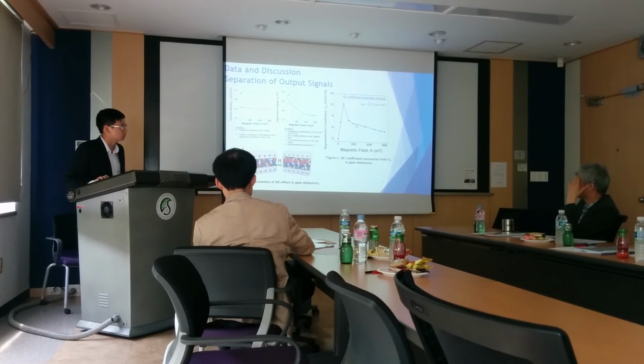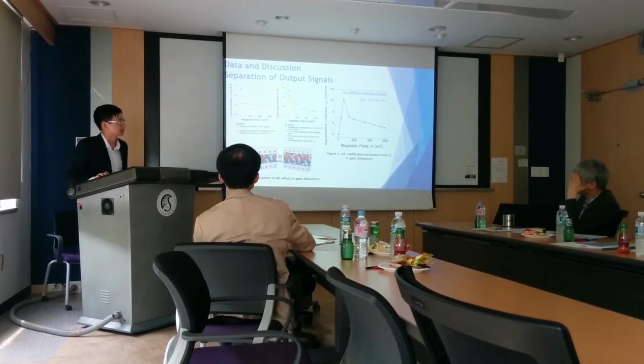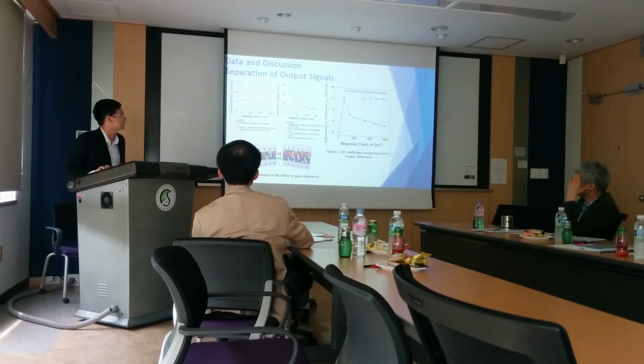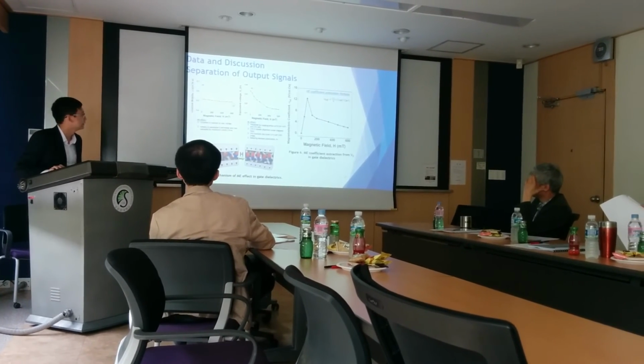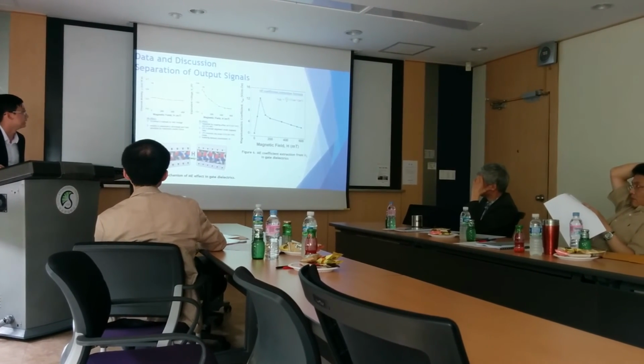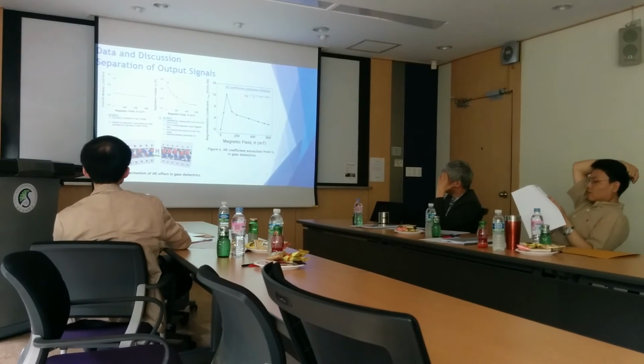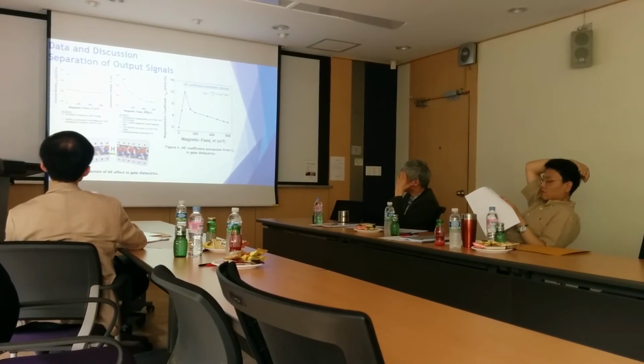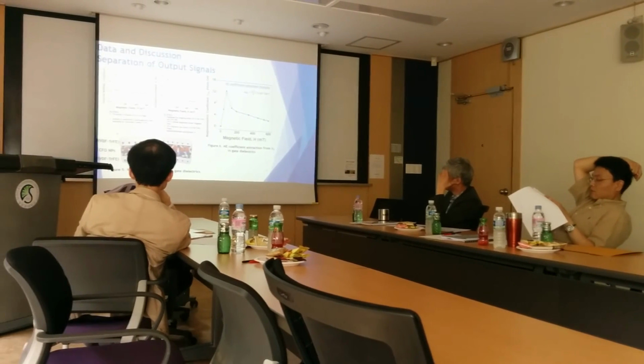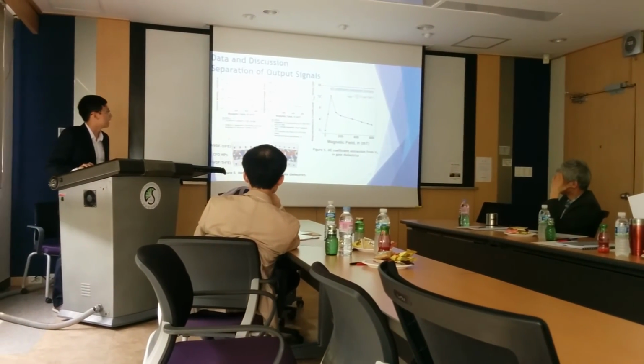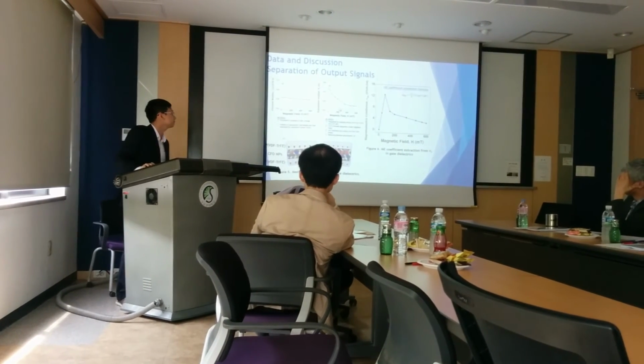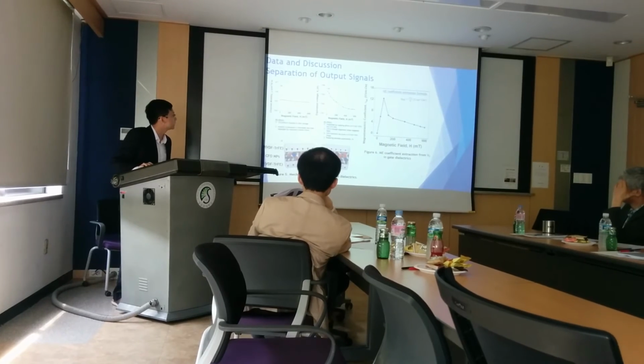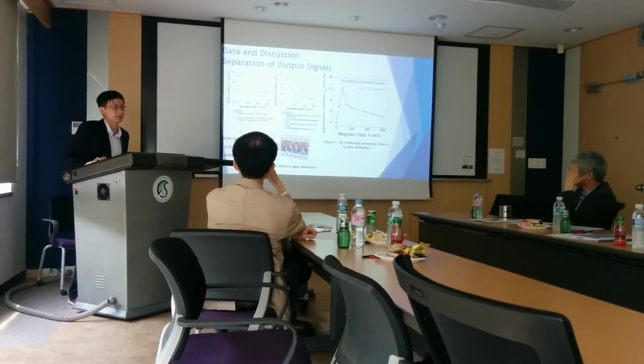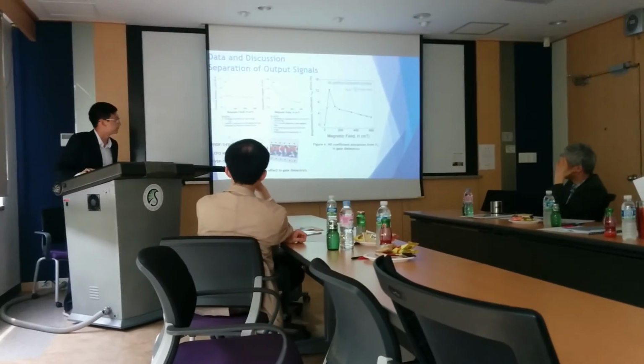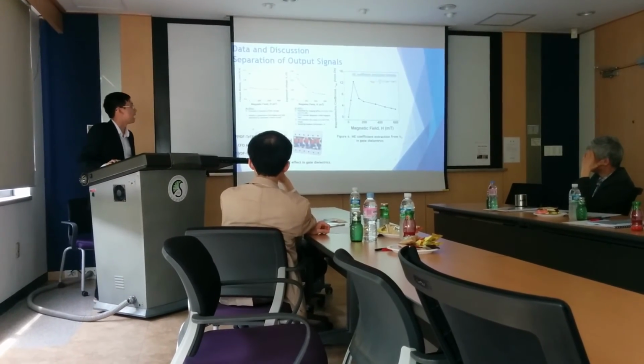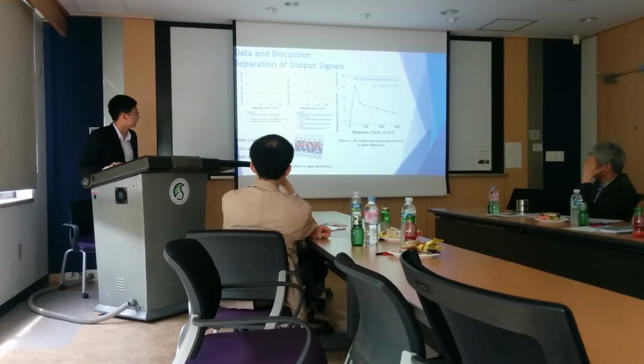To serve our proposed separation of the parameters, the important parameters we want to extract are the channel mobility in the pentacene channel and the equivalent voltage D0 in the piezoelectric material, as you can see. Both of them decrease while the magnetic field is increasing. In the case of the channel mobility, we attribute it to the magnetoresistive effect occurring in the channel by the Hall effect. I mean the Hall effect.